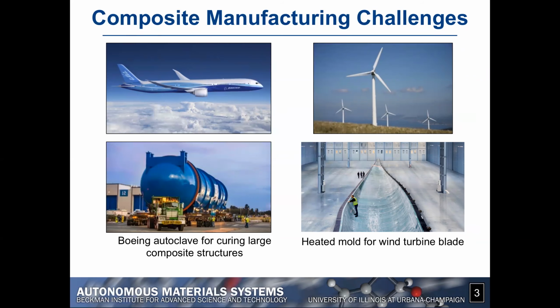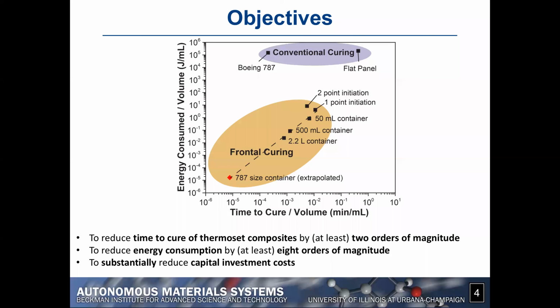And so the objective of this project is to substantially reduce this cost and really change completely the way composite materials are made. So you have here on this graph, on the y-axis, the energy consumed per volume, and on the x-axis, the time to cure per volume. The conventional way of making composites is represented on the top by the two black squares over there. As I mentioned, the conventional bulk curing process involves multiple hours. Now, obviously, since we plot the time to cure per volume, the larger the parts, the smaller this number.